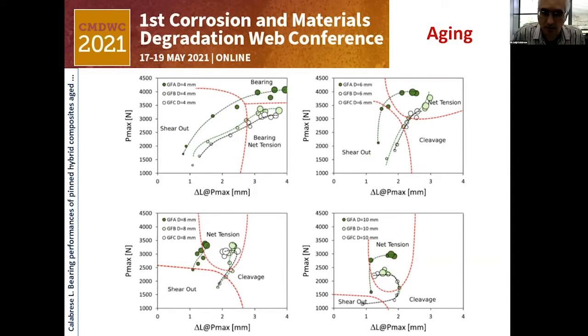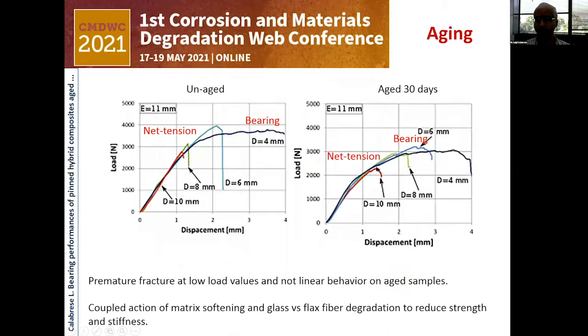And this one is a new map where we tried to summarize how the aging effect influences the mechanical performance and the failure mechanisms. We compared the maximum load and the displacement at the maximum load in order to have information on how much the curve switched from the left to the right side of this plot.